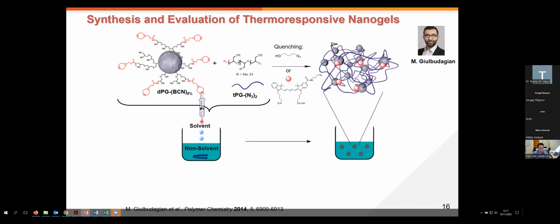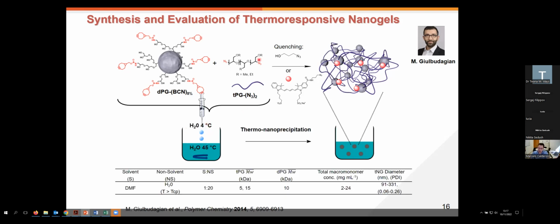Now, again, we have to play with concentrations, injection speed, stirring speed, et cetera. But we come from injecting a solvent, where we had all our polymers or precursors completely dissolved, into a non-solvent. This will generate the nucleation, and then ultimately will give us the nanogel as a product. It was very interesting because initially we used DMF as a solvent and warm water as a non-solvent. But then we started changing this strategy, for instance, to use just cold water as a solvent, because these are thermoresponsive segments, and warm water as a non-solvent, and then we just did a thermonanoprecipitation, water in water. And of course, here we could as well control sizes, functionalities, etc.